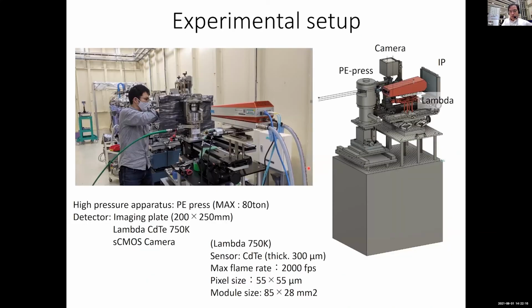So this press was used, a high pressure press, and the detector was a Lambda 750K. This is a cadmium telluride pixel detector for fast time resolved measurement.